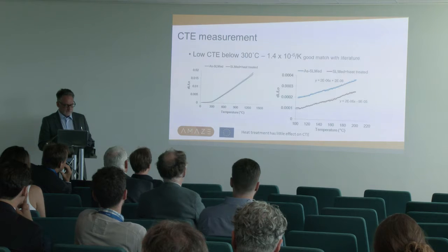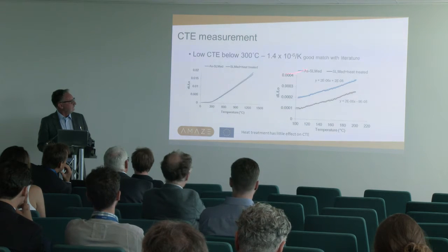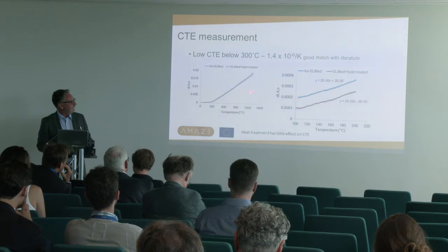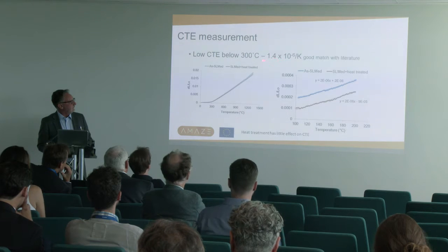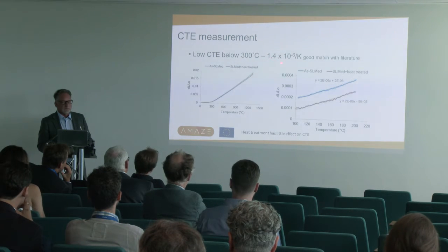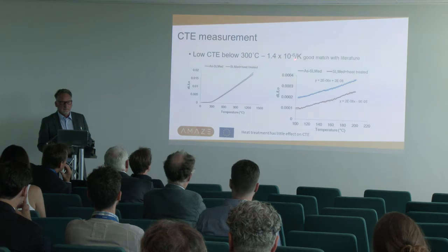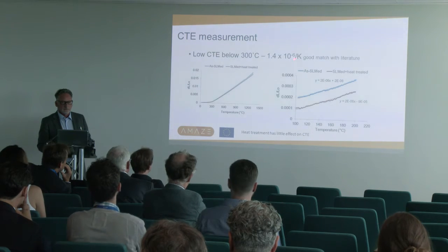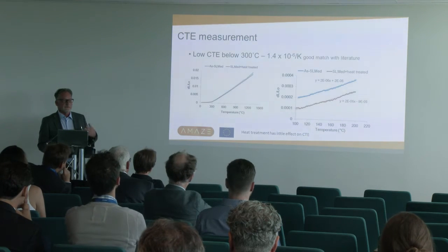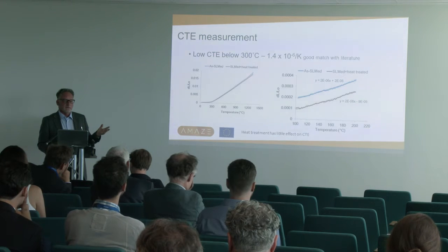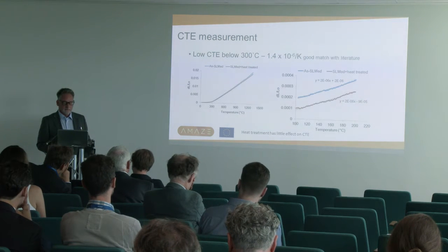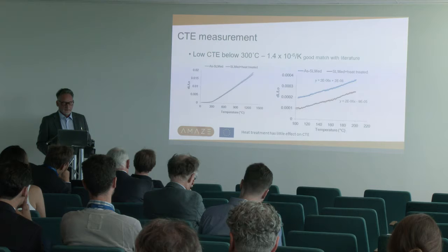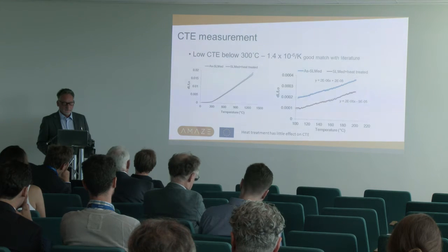So again, we produced some samples and measured the CTE of the material. And the value that you get is about 1.4, which is a good match with what's expected in the literature for this material. So this is what the material is used for. It's used for cases where the thermal expansion coefficient needs to be very low, and processing by SLM gives you that option.